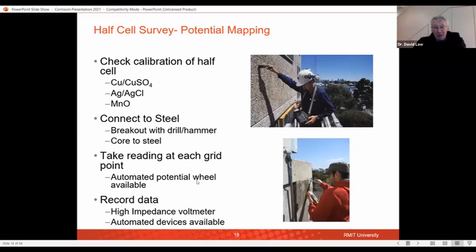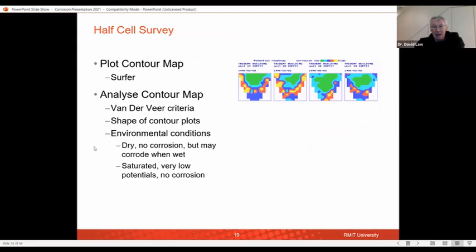You can get potential wheels, but it needs a fairly flat surface to be able to roll it along. And you also need to use a high impedance voltmeter, or you can get some of these automated devices, such as the one at the top, where it just records each time it's put on the surface. At the bottom, this was some of my research students, and so they would read out the number and someone would actually write it down to be able to produce that information.